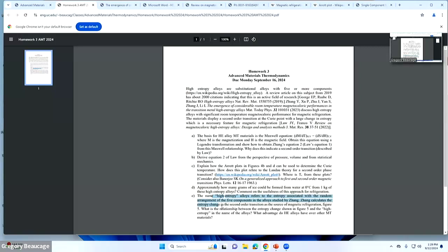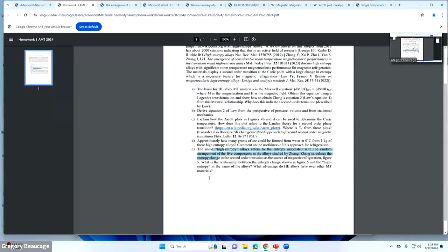And this thing is a mixture. When he says high entropy alloy, he means that he has this mixture of 5 components, and it's in a perfect FCC crystal, but the components can be located at any of the possible sites. Because of that, it's high entropy, because there's a number of different states.